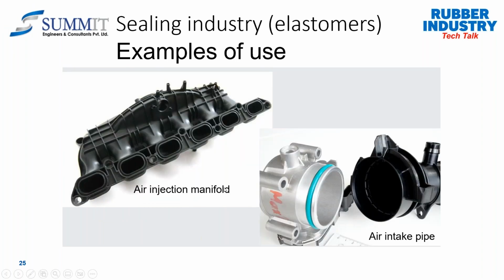Air injection manifolds, air intake pipes, where you'll find the assembly becomes very critical. And many times the failure of the O-ring happens during the assembly itself, which can be avoided very effectively by using the PTFE coated or the dry film lubricated O-rings. Normally, these dry film lubricant coated O-rings are called the PTFE coating or the molybdenum disulfide coating, which has been used in the industries.